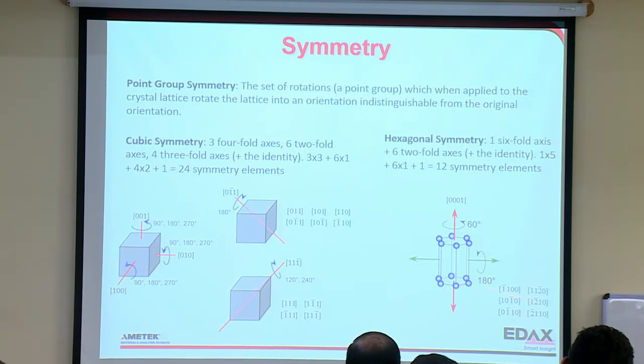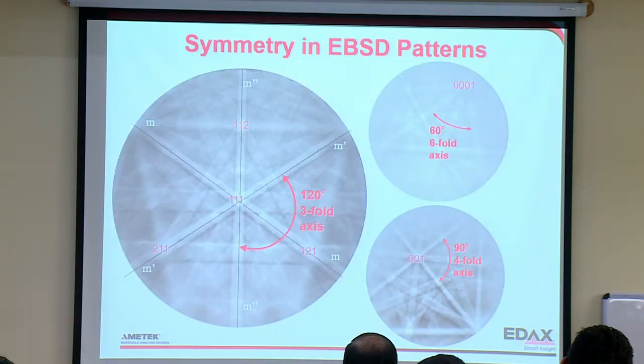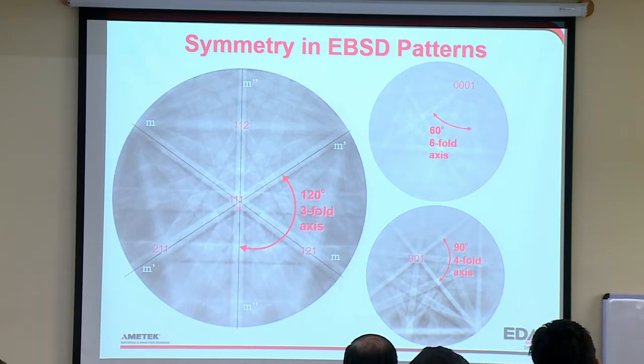And I show other examples here, but we should be able to see that in the diffraction patterns. And so this is a cubic one right here. This 111 is a threefold axis. And so you see here there's 120 degrees between those two. And you can see there's a 121, 211, and 112.